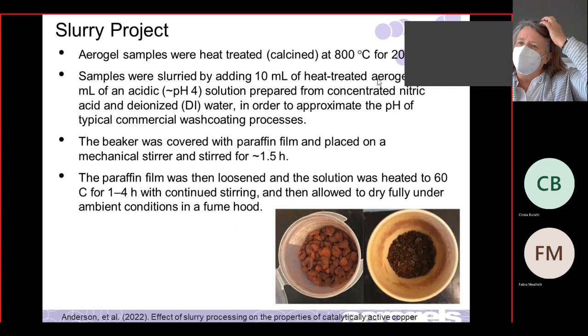They were first heat treated, as we do to all the samples, at 800 degrees C for 20 to 24 hours usually. They were slurried by taking 10 milliliters of the heat treated aerogel and mixing it with an acidic solution of nitric acid and deionized water. We crushed it up first, and then added it into the water. It's hard to get it to mix, but we stirred and heated it for about an hour and a half. Then we took the top off and heated it even higher to drive off all the water and let it dry out. And it looked like this afterwards.